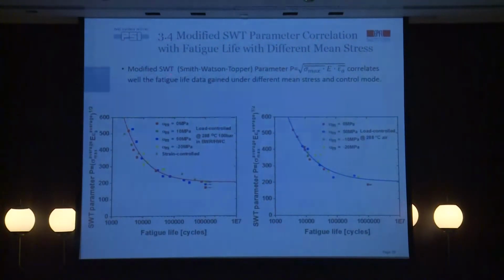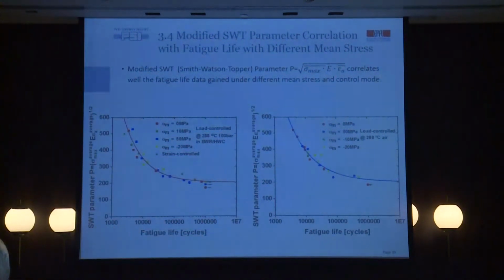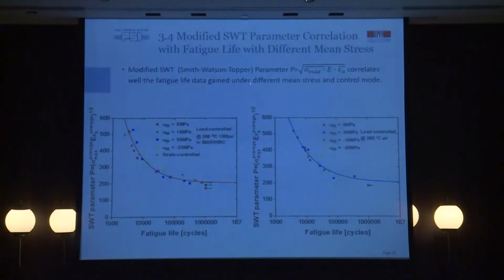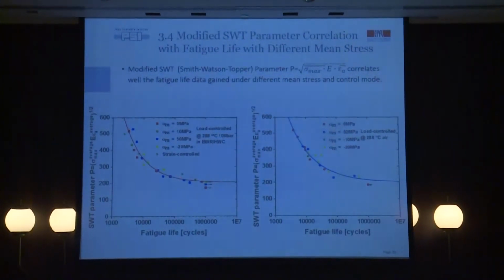So we have modified the SWT model parameter, which couples the maximum stress and the average strain. From these two diagrams of the two different environments, here in the high temperature water, here in the high temperature air, we found this modified SWT parameter correlates the fatigue life data with mean stress and with different control modes well.